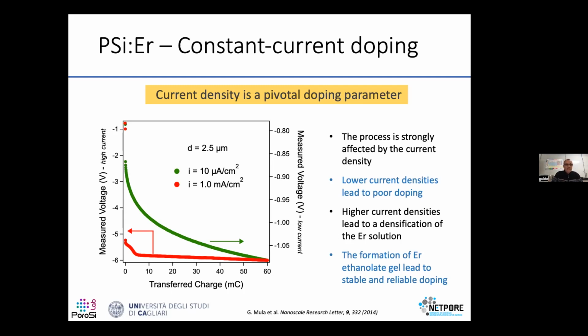However, if you go to higher current densities, then your system changes, and you have this double transient here that will also be followed by a third later on, that I will describe later. And this demonstrates that your process has changed. From a single process, you have multiple processes, the chemistry is changing. In particular, we show that these first transients indicate the transition from a normal solution to a denser solution, where the formation of erbium ethanolate gel led to a stable and reliable doping, while for lower current density, you are putting erbium, but this erbium is not fixed on the surface. When you wash your system, it will directly go away.